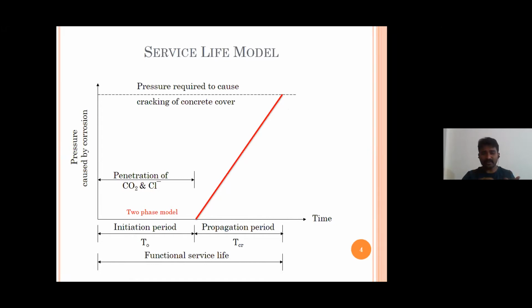Once the corrosion product fills the porous zone thickness, it starts exerting the expansive pressure. Once that expansive pressure is more than the tensile strength of concrete, then the cracks will start appearing. So that total time from corrosion initiation to corrosion cracking, we call the functional service life. And Tuutti has divided this functional service life into two stages: one is the initiation period and one is the propagation period.